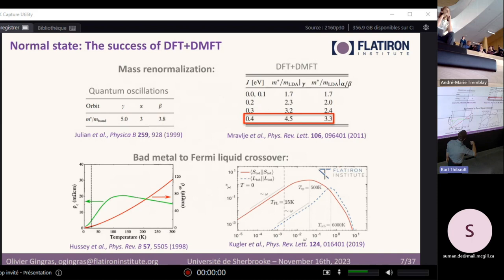Another success from DMFT is the description of the bad metal to Fermi liquid crossover in strontium ruthenate. Strontium ruthenate is well known to have a very beautiful Fermi liquid regime at pretty low temperature, 25 Kelvin. And above that, there's a lot of incoherent scattering. This is kind of a hallmark of a Hund's metal, where you have a differentiation between the orbital degrees of freedom and the spin degrees of freedom, so that these degrees of freedom will freeze at different temperatures.